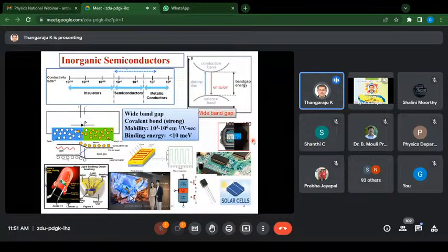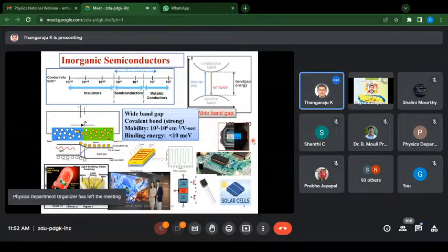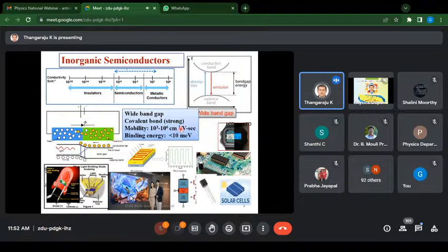If you look at the usage of energy, mostly it is used for lighting as well as displays. Displays and lighting are the major sources which consume a lot of energy worldwide. The device used for harvesting solar energy is the solar cell. All these devices are made of inorganic semiconducting materials. Inorganic semiconducting materials are wide band gap and mechanically stable, with higher charge mobility between 10^3 to 10^6 cm^2/V·s, and less than 10 milli electron volt binding energy. So they can be easily excited and the energy can be released, even in the visible range.